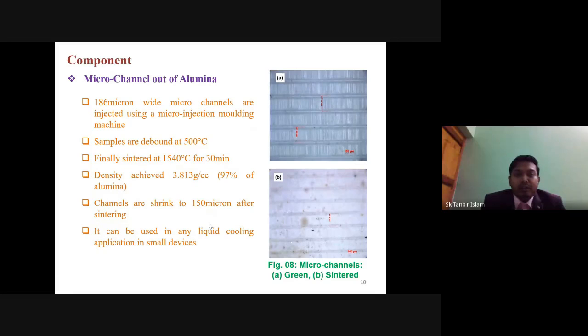We made a microchannel out of alumina. We prepared an alumina feedstock and then injected it into a die, where the microchannels are made. We have two samples: one is the injected one, and the second one is the sintered one. That component is debound at 500 degrees centigrade and sintered at 1540 degrees centigrade for 30 minutes, and we achieved 97% of the density of alumina. This component could be used for cooling purposes in small devices.